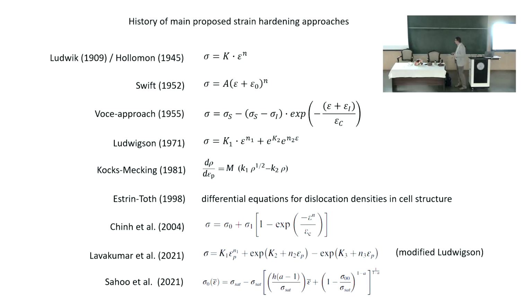You can find here four parameters: saturation stress, an H parameter, and an A — that's already three — and then sigma zero, which is the initial flow stress. Usually the initial flow stress is known, you just put it into the equation, you don't have to fit it. So if you don't count that, it's only three parameters.